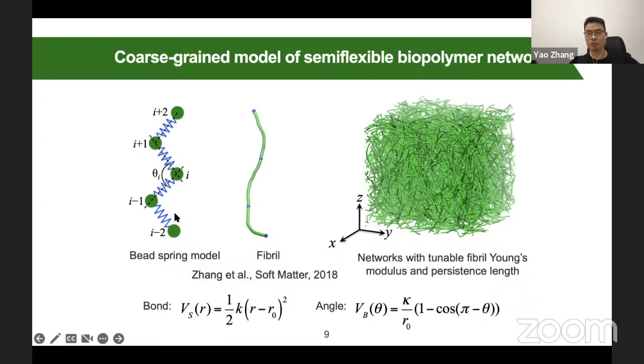So we use this bead-spring model. I think most of you know this method very well. Basically, you have a lot of beads that are connected by bonds and springs. The bond gives you the Young's modulus, and the angle gives you the persistence length. Usually, based on chain models, we can generate the network structure. For this network structure, at first, these fibers are just randomly distributed, and then we add crosslinks between the fibers to generate this crosslinked fiber network.